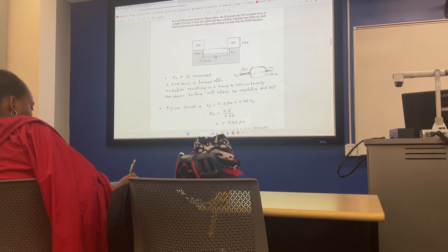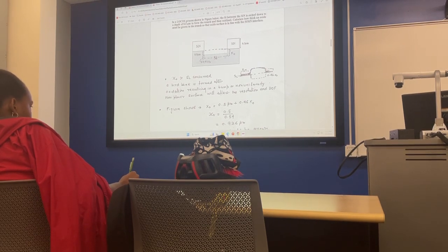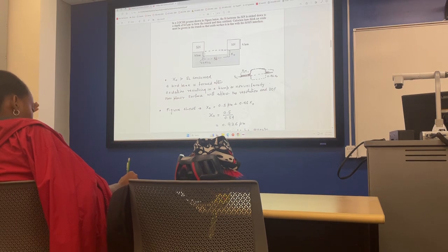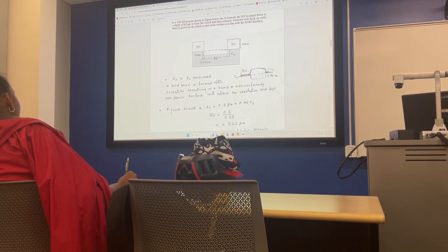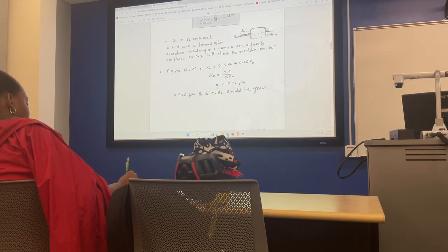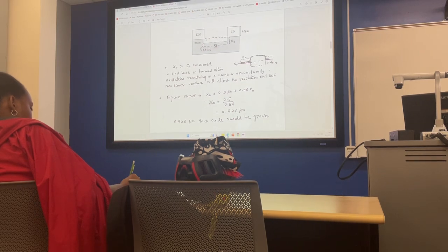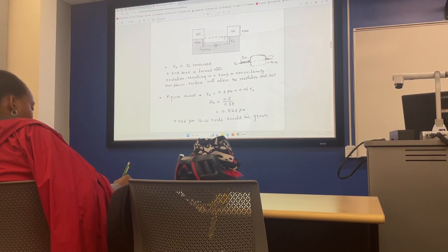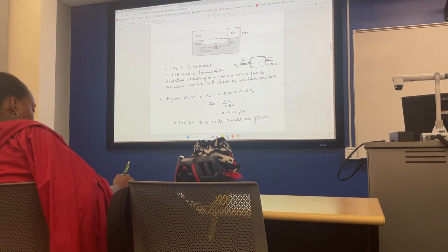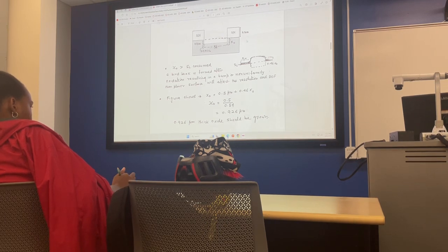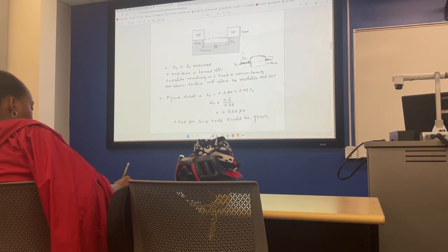So if you realize what's happening in this trench, x naught, which is the total oxide thickness, is the sum of the 0.5 micron trench and the 0.46 x naught that you ate, and that gives you x naught of basically 0.926 micron. Okay. So if you grow that 0.926 micron total oxide thickness, then you will have a flat area here, with an oxide separating the device you will make here and the device you will make here. So that was the question.